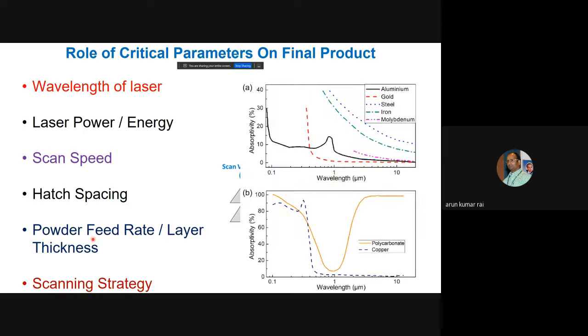So first you take the wavelength. Now here I am giving you the absorption of different materials. You can see here aluminum, gold, steel, iron, and moly. If you take aluminum, the maximum absorption is at 0.1 micron wavelength. If I take 1 micron wavelength, which is what we conventionally use with an Nd:YAG laser or Yb-doped fiber laser, the absorption is very low, less than 5%. So this is not suitable at all for additive manufacturing of aluminum.